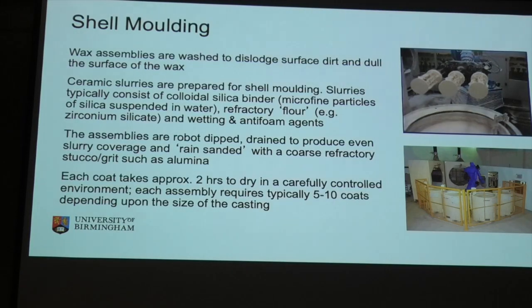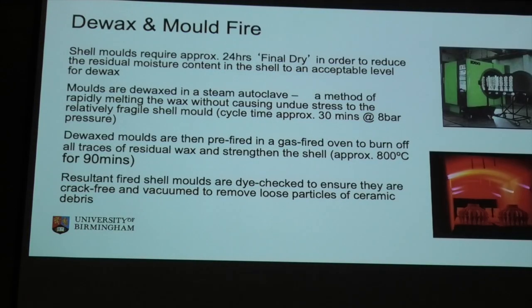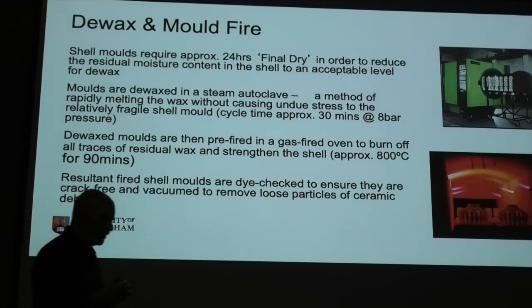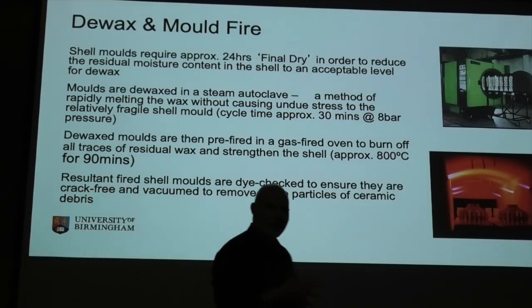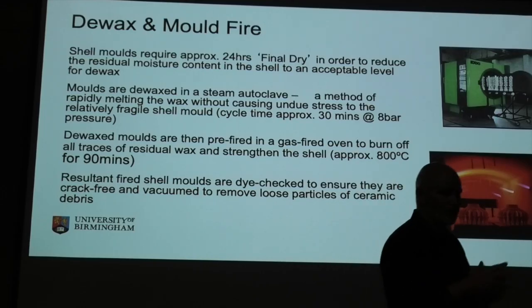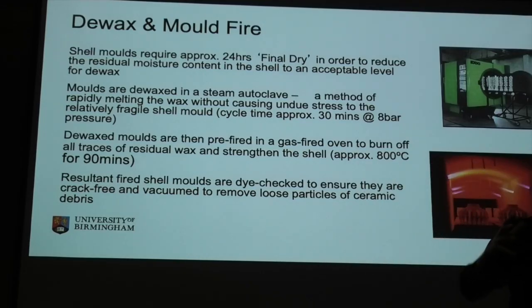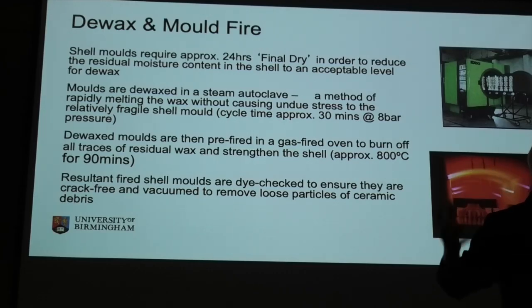So we're going to dry it for 24 hours, it's still not particularly strong, and we're going to stick it in a machine that looks like the one at the top there. We could use a furnace, but we can't heat it up slowly to melt the wax out. Although it melts at 70 degrees C, if we heated it up slowly, the wax would expand. The shell isn't very strong, it would expand and blow apart, and we'd end up with crumbs in the bottom of the furnace. We've tried it.